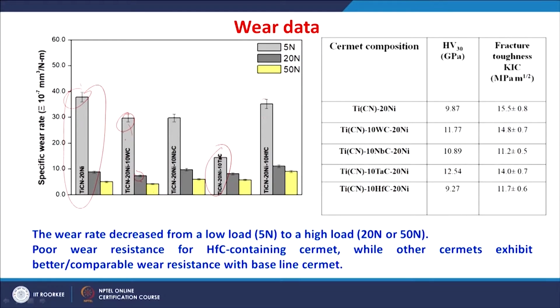We can actually relate this with the mechanical properties. The cermet having higher hardness shows lesser wear, and the one having the lowest hardness shows higher wear. But you can see there is not much relation between the fracture toughness and the wear. This may be related to the absence of any cracking at the interface of the core and rim or the binder, which will be seen in the next slides.